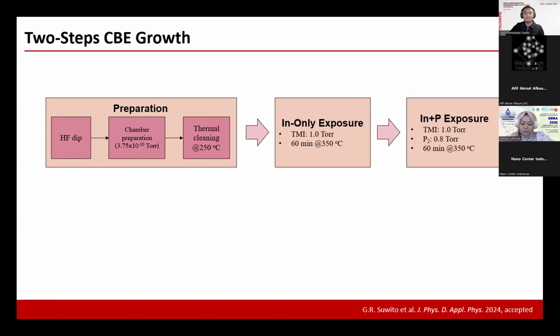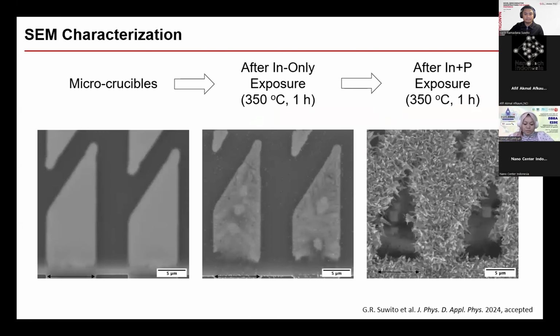And to grow indium phosphide, we use a two-step growth strategy. After a series of preparation steps, we expose the microcrucible with only indium precursors for 1 hour at 350 degrees C, and then we simultaneously expose the sample to indium and phosphine for another 1 hour. This is how the microcrucible looks under a plan view SEM before the growth. So it's a top view, with the double arrows indicating the location of the opening. The precursor would go from here to here, from this opening only, and everything else is covered.